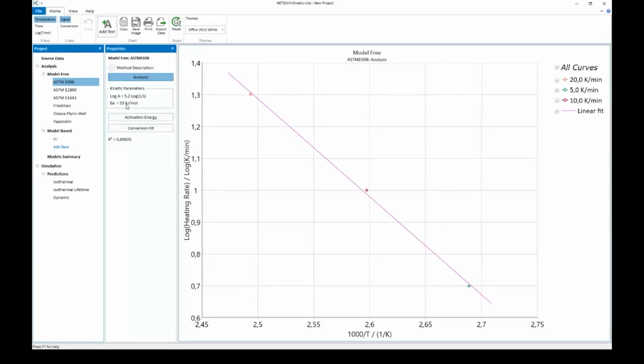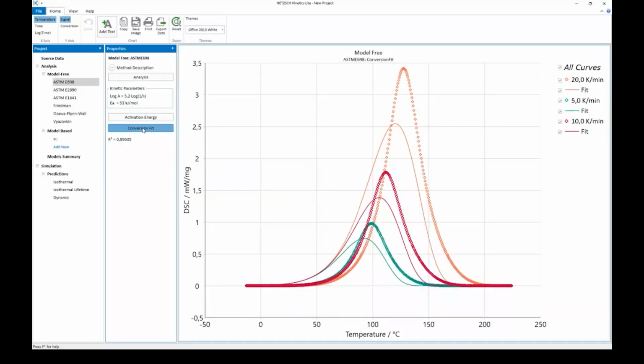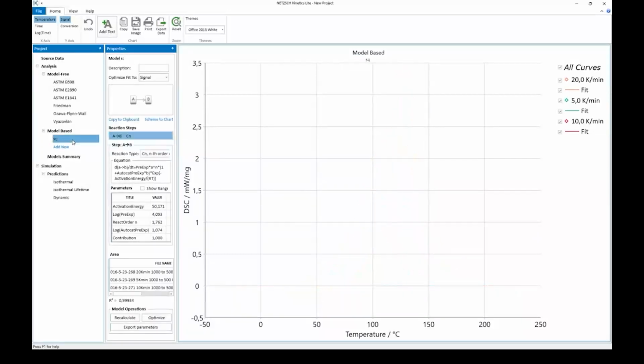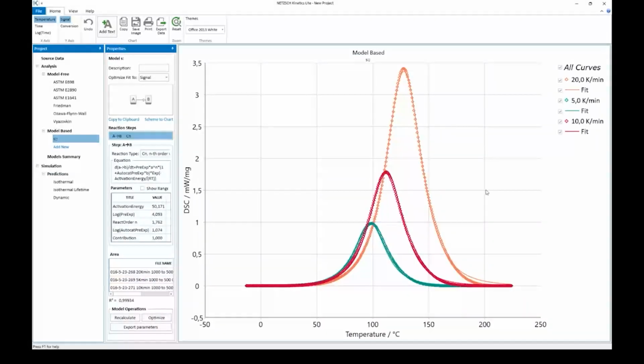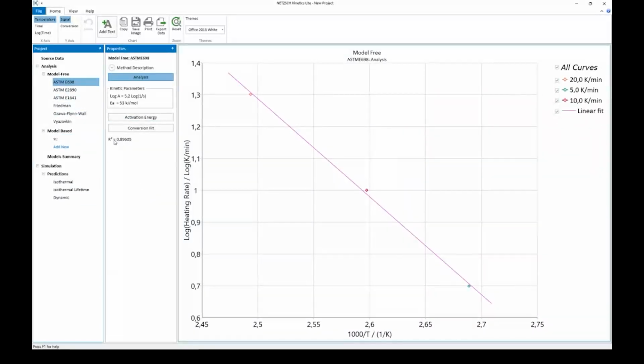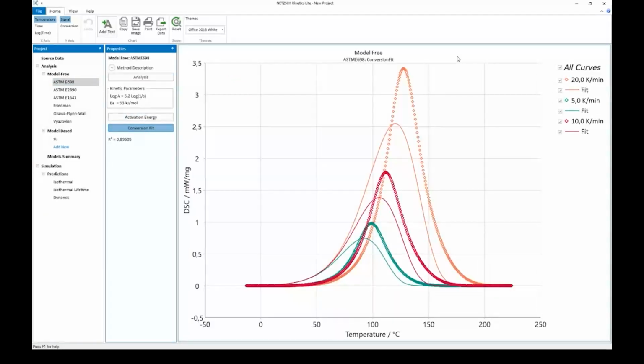We can just see here the conversion fit. Is it good? It is not as good as our model-based kinetics. So here the fit is good, R square is 0.999, and at that time R square was 0.89. So it is really not good. What is important: you must always see the fit.